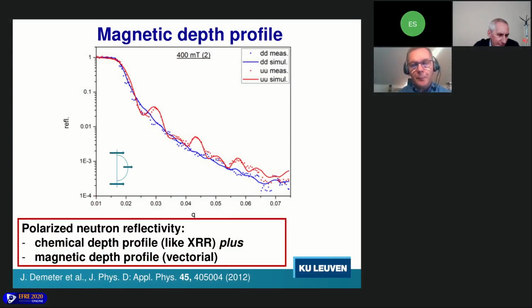And this is what I show here. So this is a reflectivity curve measured with up neutrons, these are the blue dots, and with down neutrons, these are the red dots. And the blue and the red lines are a fit to the data. So what you see here is the reflectivity plotted as a function of the scattering vector, or you could also plot that as a function of the 2 theta angle, just like in X-ray reflectivity. So what polarized neutron reflectivity does is that you measure the chemical depth profile, like in X-ray reflectivity, but additionally, you also measure the magnetic depth profile.